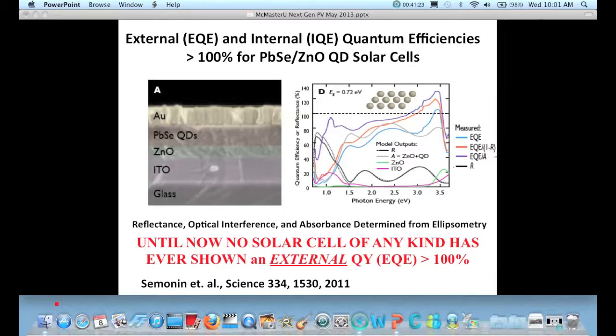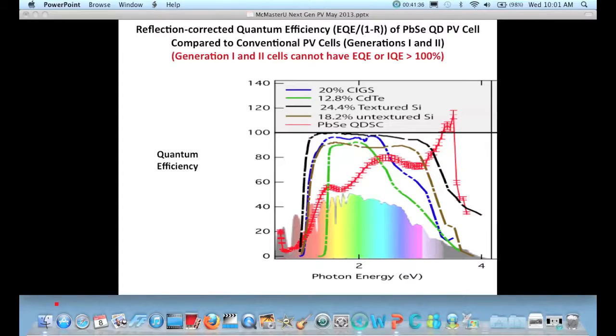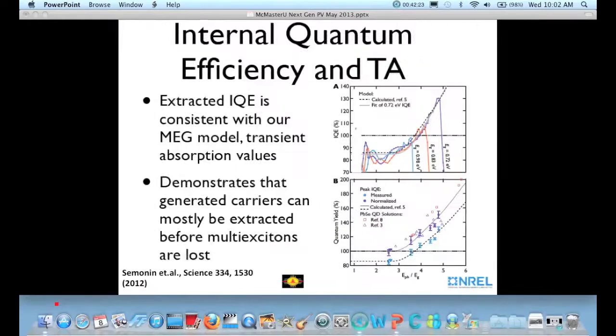And when we measure the quantum yield and model the optics of this solar cell, you can see that there's a region here where we get a quantum yield greater than 100%. Now, no solar cell today has a quantum yield greater than 100%. So this is CIGS, cadmium telluride. The best that can be done is this silicon cell with textured surface, which has a quantum yield of 100%. But over here with these lead selenide quantum dots, we can get a quantum yield greater than 100%, approaching 135% when you correct for reflection. And you can see that there's still a loss in the cell because there's normal electron-hole recombination even before you reach the threshold. The threshold's at a little less than 2.6.